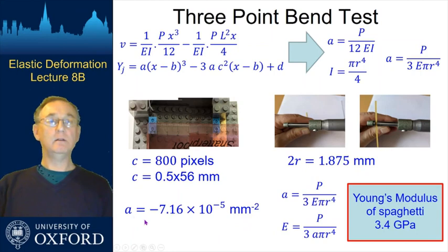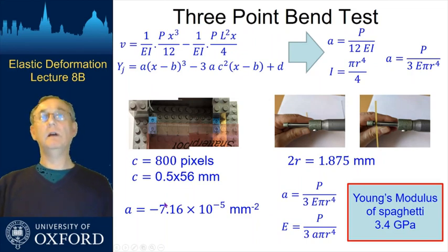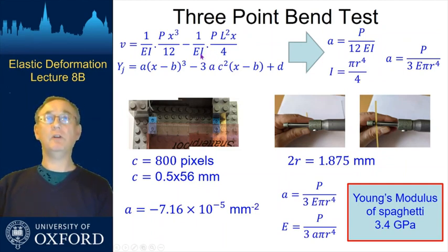And if I do that, the value of A comes through to this thing in here. The minus sign is just from the fact that the plus or minus direction on the deflections was wrong in the images. So don't need to worry about the minus sign. And the other thing we need to do is just work out what this thing in here is, the second moment of area. And for a circular cross section, you can work that out or look it up in textbooks. It comes out to be pi times the radius to the power four divided by four. So I need to measure the radius. And here you can see me just zeroing a micrometer and then measuring off the diameter. So twice R of the pasta, which was a little bit under two millimeters.